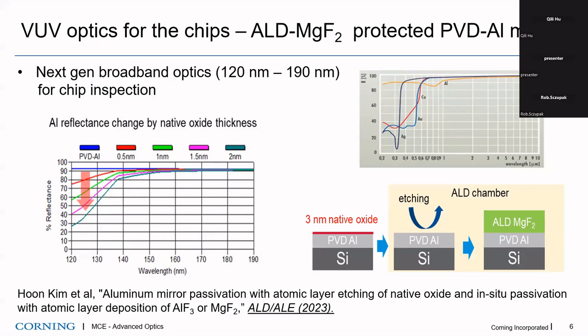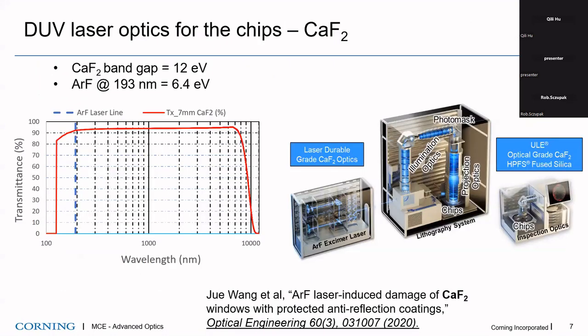And now further step into DUV, right? DUV in this case represents 193 using an excimer laser. And so calcium fluoride becomes the material of choice for 193 laser optics, because of the wide band gap. 193 nanometers corresponds to